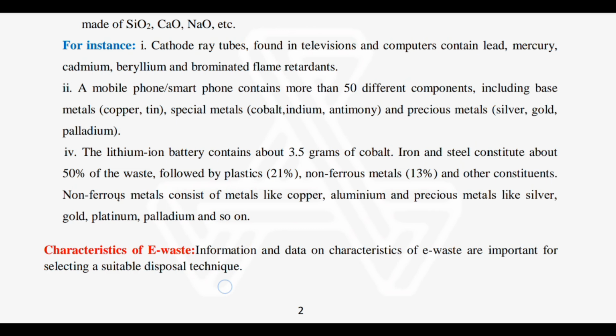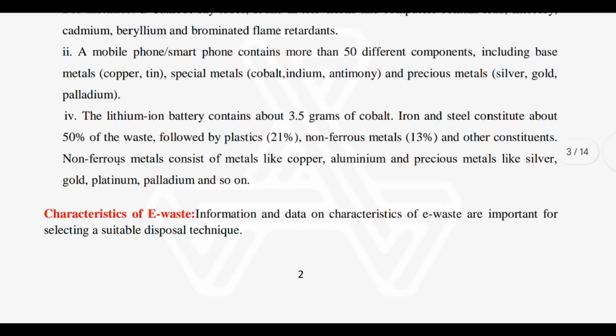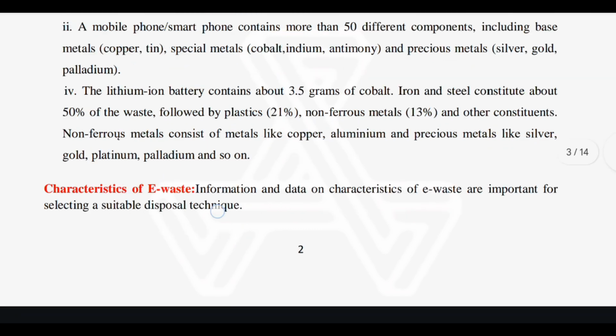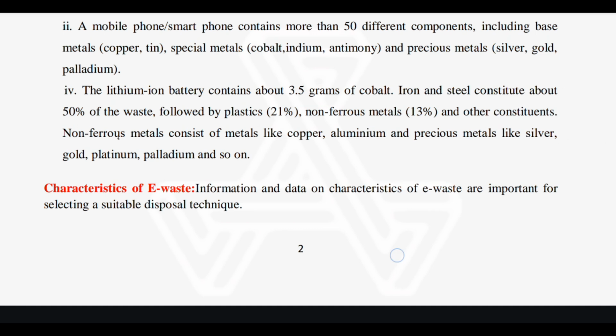For instance, cathode ray tubes found in televisions and computers contain lead, mercury, cadmium, beryllium, and brominated flame retardants. A mobile phone or smartphone contains more than 50 different components, including base metals like copper, special metals like cobalt, indium, antimony, and precious metals like silver, gold, palladium. The lithium-ion battery contains about 3.5 grams of cobalt. Iron and steel constitute about 50% of the waste, followed by plastic 21%, non-ferrous metals 13%, and other constituents. Non-ferrous metals consist of metals like copper, aluminium, and precious metals like silver, gold, platinum, palladium, and so on.